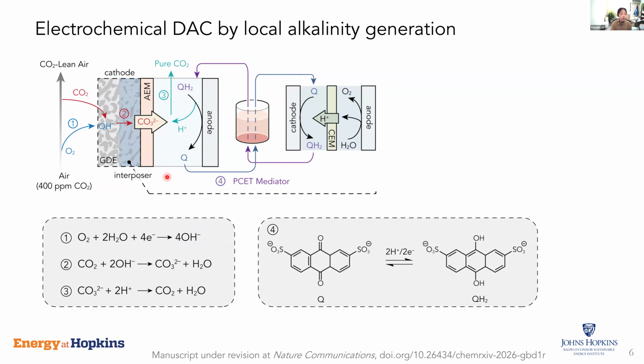And at this anode side, we're using what we call a proton-coupled electron transfer mediator, or PCET mediator, which is in this case a small molecule that can reversibly exchange protons with the electrolyte upon electrochemical trigger. So this proton release can react with and acidify this carbonate and release a pure stream of CO2 without the need of downstream purification. And this reactor can later be regenerated through a reverse reaction to get protonated, and that is done through another smaller scale electrochemical reactor.